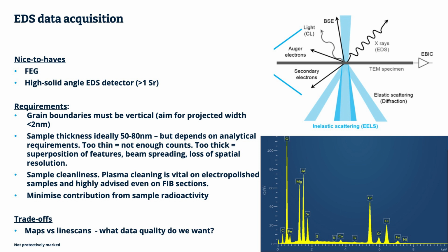For EDX, you can definitely have samples that are too thin. You just don't end up with a lot of counts coming out of them. And too thick results in too much beam spreading within the sample. And that will degrade your spatial resolution.